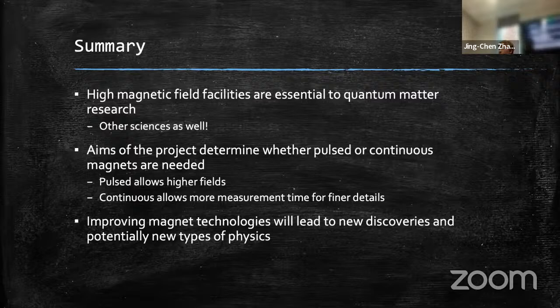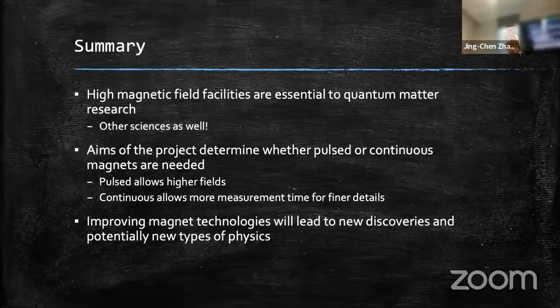I see. What about something like the resistivity dependence on temperature in high magnetic fields? Are there any new behaviors other than some Drude model or something? Yes. The material I'm working on happens to have what is referred to as extremely high non-saturating magnetoresistance. In normal materials, magnetoresistance is quadratic up to some point, at which it saturates, and no matter how much more field you put in, your resistance is not going to change much. In some materials it can stay quadratic, or under different physics it can even be linear, up to the limits that we can push to. And it's interesting.